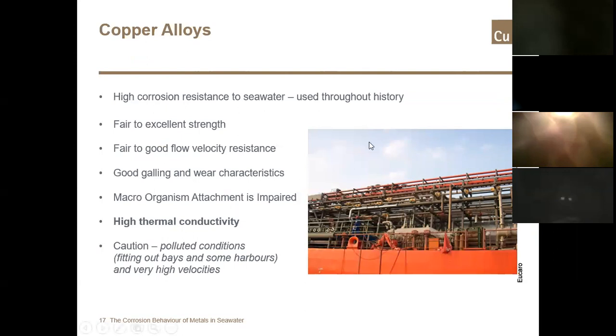The development of copper-based alloys has allowed a wide range of properties to be met, with strength levels available up to 1500 MPa, hardness values up to 45 HRC. The copper alloys can more than match strength levels associated with ferrous materials, such as stainless steels, nickel alloys and high strength steels. And copper as a whole offers low general corrosion rates in static seawater, approximately 0.02 millimetres per year, and has little tendency to pit. However, they also offer a very useful resistance to flowing seawater, and can even handle moderately high velocities at intermittent periods.